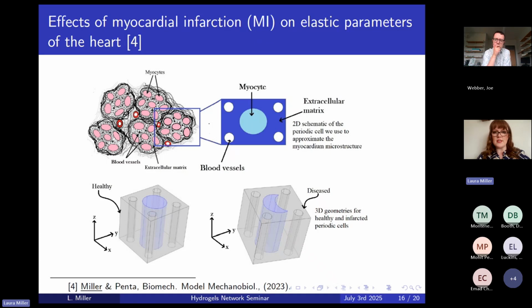For homeostasis reasons, the heart has to then produce a thick collagen-rich scar that bridges over the gap where the myocytes have died, and it does this in a way that retains the structural integrity. However, although the structural integrity is there now with that scar, the efficiency is damaged because the heart cannot contract as well with this very stiff piece of tissue in